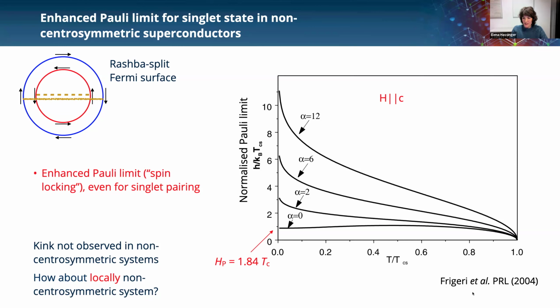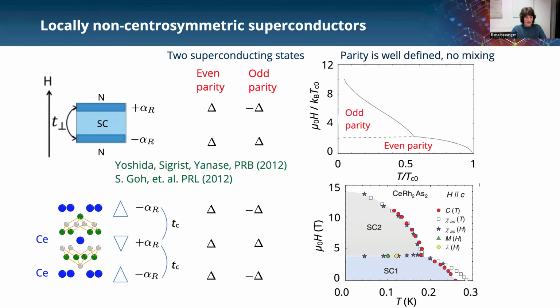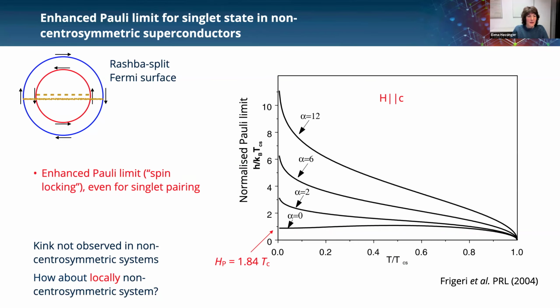Frigeri and Sigrist and co-workers have calculated the Pauli limit for different values of the Rashba spin-orbit coupling, and you can see that it's strongly enhanced. And this is for fields along C, but also a bit reduced for fields in the plane. So that's how we currently understand the anisotropy of the critical fields in non-centrosymmetric systems. However, in CeRh2As2, there is no kink anywhere. So this locally non-centrosymmetric feature must play a role.